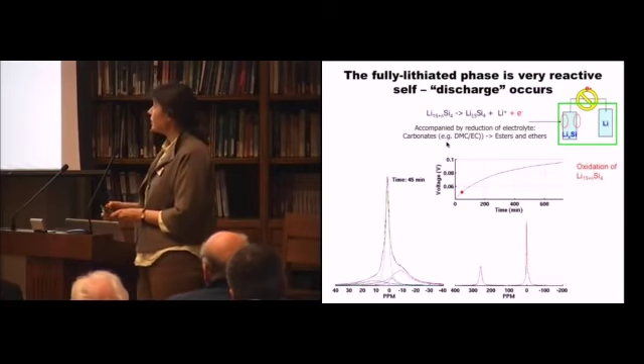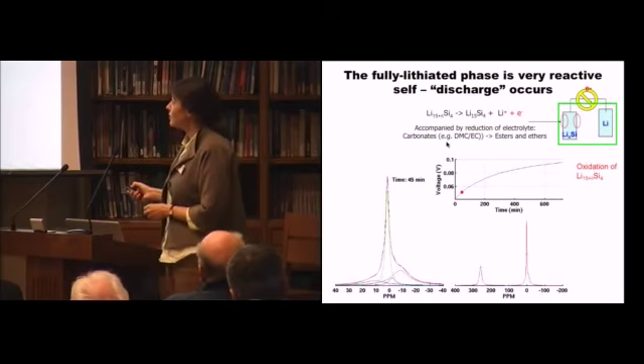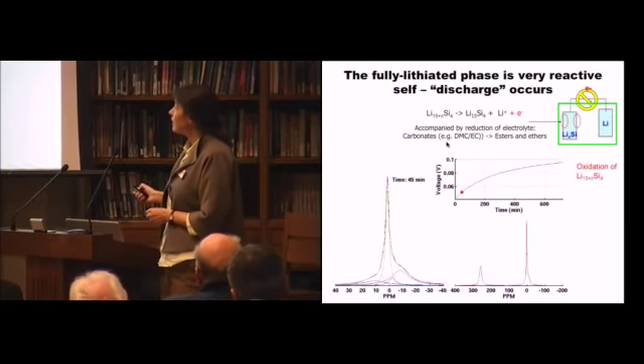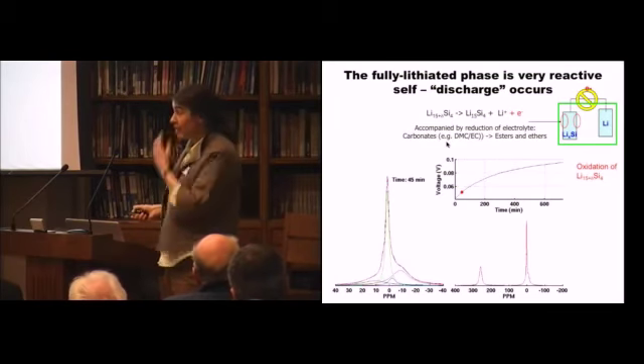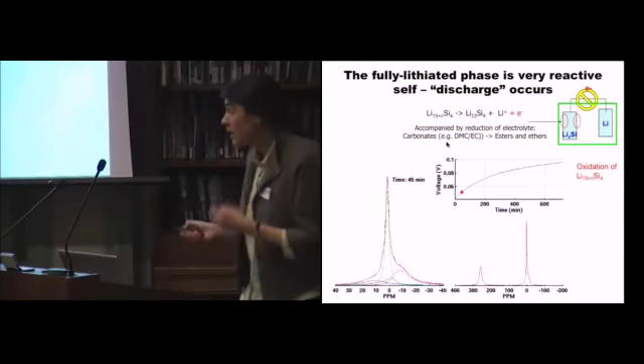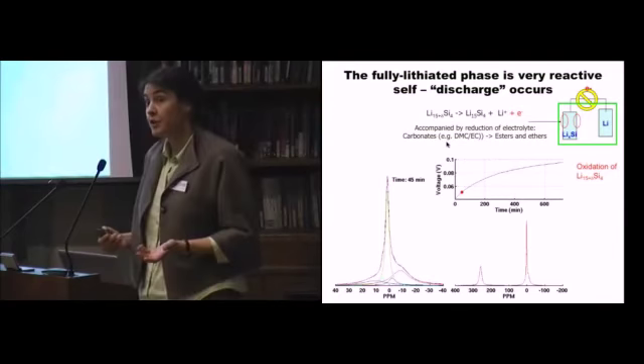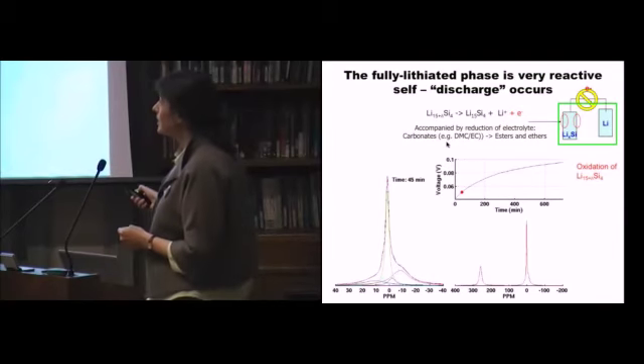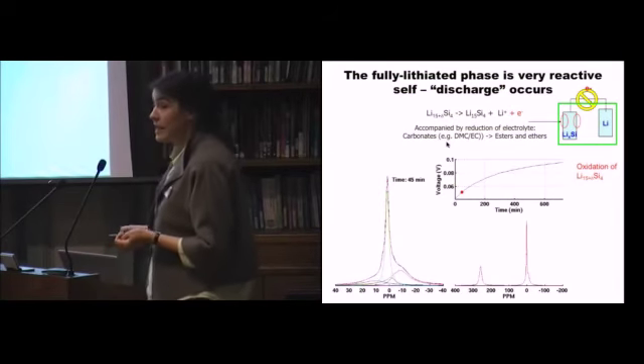And so the mystery was actually solved when my student left a battery he'd discharged, and he went away for 600 minutes, had a long coffee break. When he came back, the chemistry had completely changed. And so what's going on is a so-called self-discharge process. Your lithium silicides are so reactive, they react with the electrolyte, and they themselves are oxidized. So you've lost that negative peak.